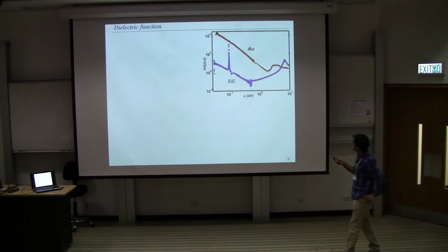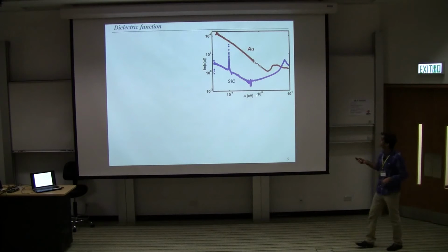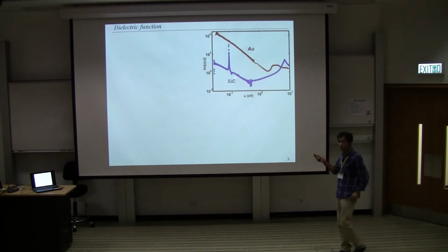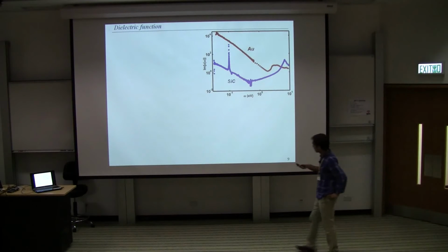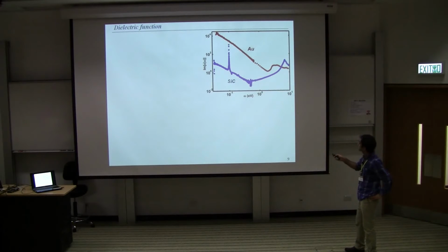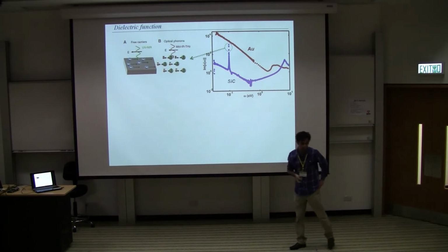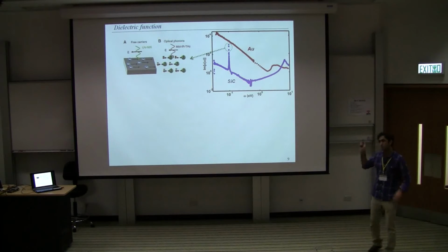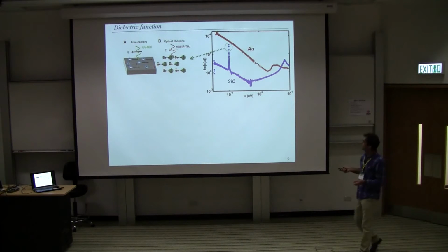Here we have experimental data we got from ellipsometry in the short range of frequency for silicon carbide. I put gold in also, because it's the most used material in these experiments, to get an idea of the difference. Here we have this peak for silicon carbide because of the effect of the surface phonon polariton in the range of about 11 micrometer, which is the property that makes it suitable for optomechanical devices.